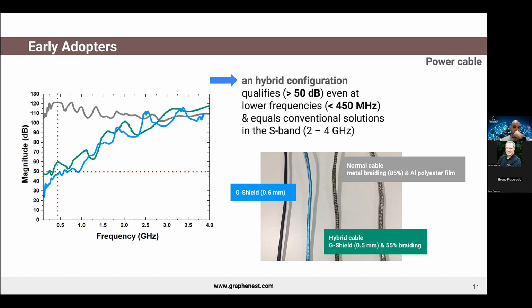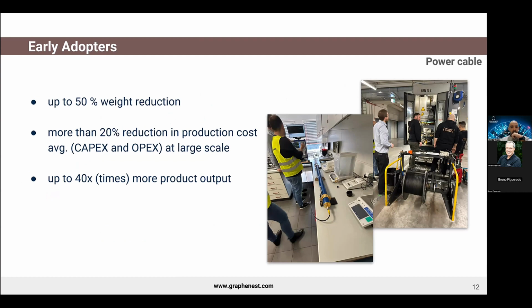And this design, like I was saying, qualified, so more than 50 decibels, even at lower frequencies, so less than 450 megahertz. And actually, it equals conventional solutions in the S band, so 2 to 4 gigahertz. This innovative shielding solution, or this design, in this case, offered great benefits. Substantial weight reduction up to 50%, cost savings, more than 20% reduction in production cost, basically because of OPEX, and increased product output up to 40 times, because in this case, the bottleneck is the braiding. So the power cables need braiding, and the bottleneck of production is the braiding process, which is very, very slow.